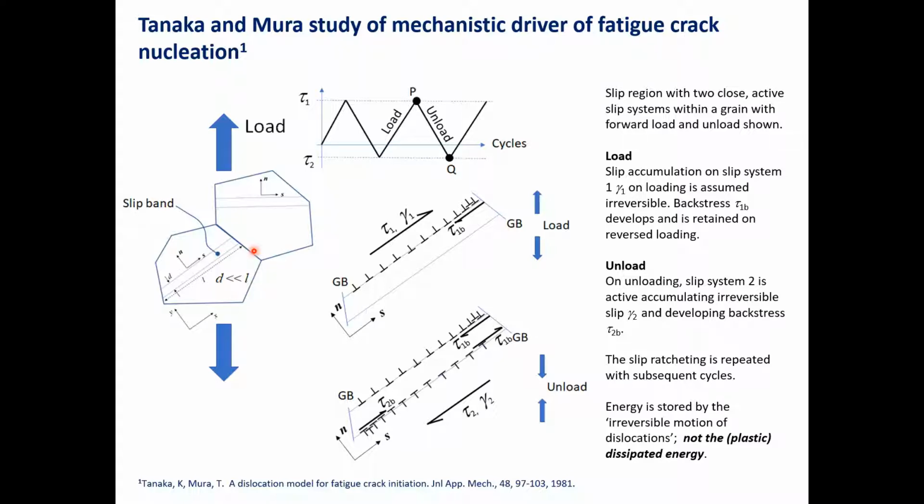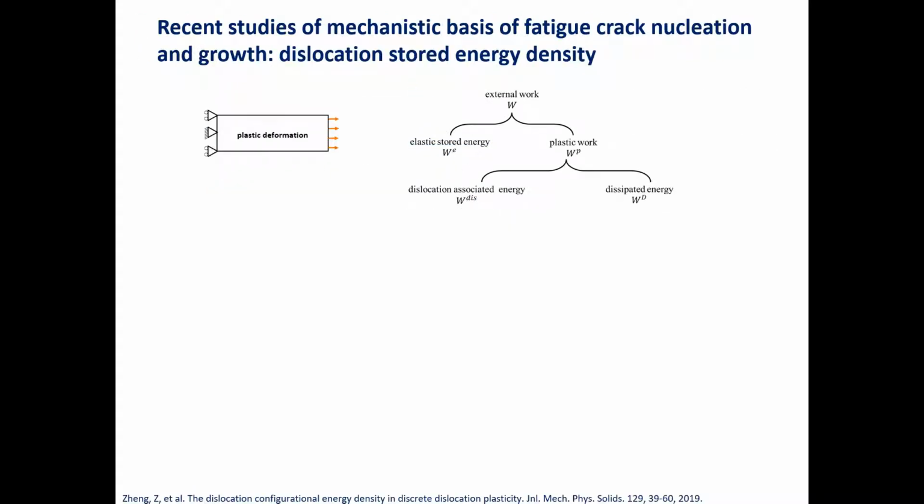But of course, what Tanaka and Mura did make clear is that there is a progressive process of the development of dislocation structure where they pile up, and often there's lattice curvature associated with that, and that is a mechanism by which energy can be stored, and it's free energy because it's recoverable in the configuration or structure of the dislocations as they pile up and form within the microstructure. So this is a key issue that we've built upon in looking at dislocation methods to understand fatigue crack nucleation